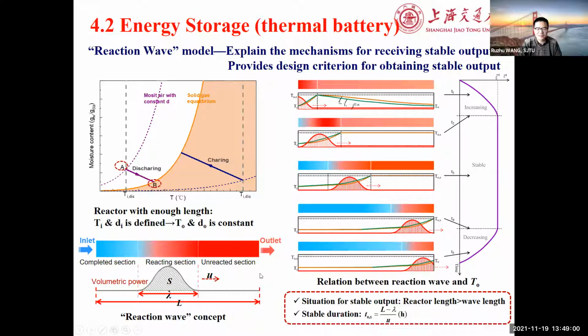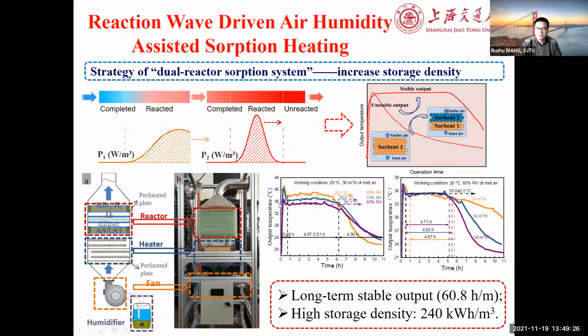If we set about 5 hours or 8 hours, you can see that the temperature output goes up and then becomes stable. This time is needed for our design, relative to the length of the adsorption bed. And after that, it will go down. So in this case, we need the output at a stable temperature. So this is for the chemical thermal battery.